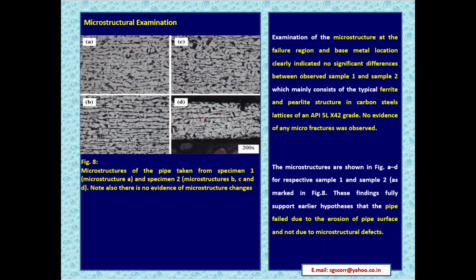Figure 8, microstructural examination. In Figure 8, A represents the microstructure of the specimen 1, whereas B, C, D represent the microstructures of the specimen 2. And you can easily observe from the above four microstructures, there is no evidence of microstructure changes. Examination of the microstructure at the failure region and base metal location clearly indicated no significant differences between the observed sample 1 and sample 2, which mainly consist of the typical ferrite and pearlite structure in carbon steels, lattices of an API 5L X42 grade. No evidence of any microfractures was observed.